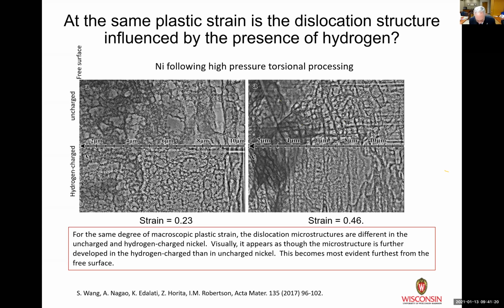So why is that important to point out to you? Well, one of the things that it should tell you is that we've made assumptions before about how dislocation microstructures or how plastic strain evolves in the absence of hydrogen, and we've said they're the same. They can't be, because clearly one is moving faster than the other. So do we, as we do the modeling that Petros likes to do, is he using the right expressions, the right formula in the presence and absence of hydrogen? Or is there still work for him to do to actually find out why it's getting this accelerated structure? It's not the same correlation between microstructure and strain. There's something different in hydrogen. And I challenge Petros and others in this area to say, do we have the right model yet for putting the hydrogen effect into those models?